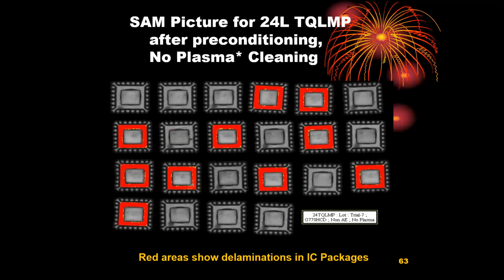But when we did the plasma etching or plasma cleaning of the materials, we found that plasma etching or cleaning was actually better, as it did not give rise to any oxidation or contamination or any other things. And then the adhesion or the wettability was much better, and then it gave rise to fewer delaminations. So without plasma cleaning, initially it was bad. I want to show you the worst case picture, to be very honest.